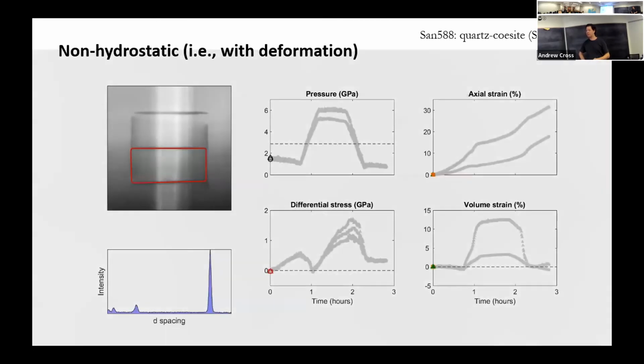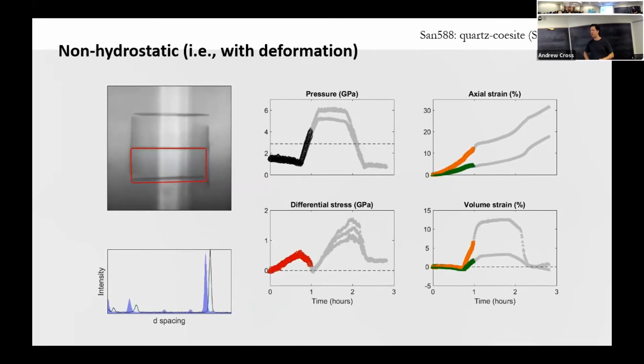So let's play through. We're now deforming and waiting to see if we get to some sort of steady state. The sample ends up straining at a steady state, but the stress is still going up. We start our pressure ramp here. We get a big drop in differential stress all the way down to 0 as we transform to coesite. Then the sample hardens and strengthens up again to some sort of new stress state. Stresses here are on the order of a GPa, slightly more than a GPa.